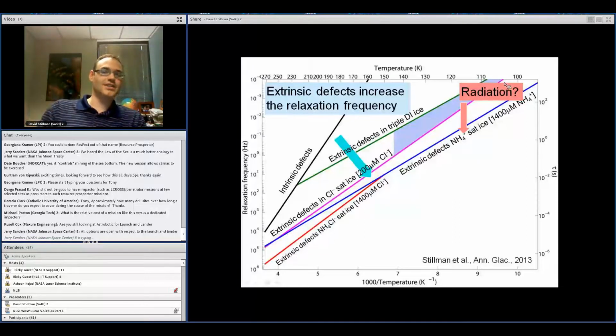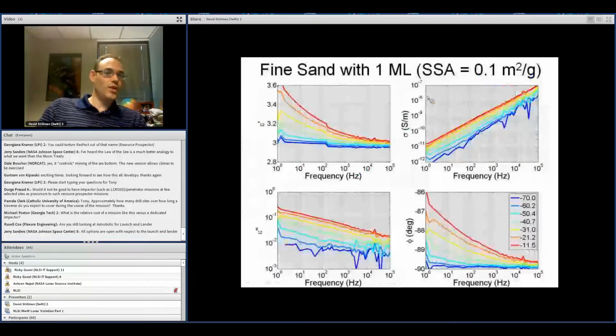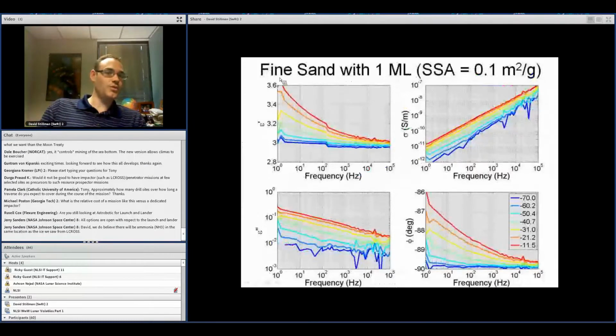So this means we can only detect subsurface ice if we have an area where the ice has a temperature of above 100 K. The radiation may actually allow us to see into colder areas, but we still need to test that. So then, moving away from ice and now going into adsorbed water, this is a fine sand with one monolayer.